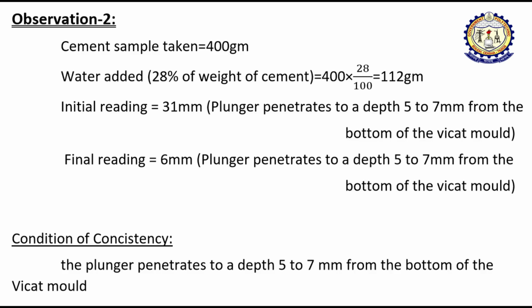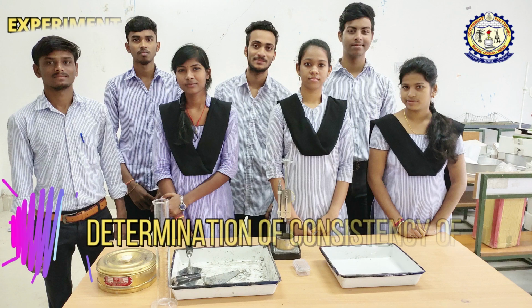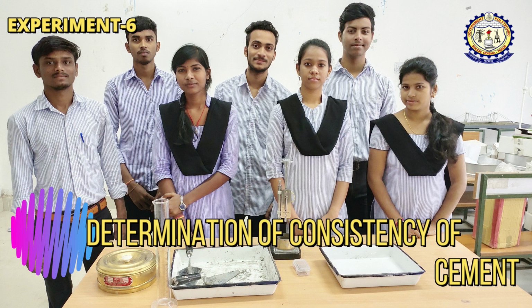In the second observation, we find the final reading is 6 mm, and this value satisfies the consistency condition, so the consistency of our cement is 28%. We can directly say the percentage of water required to achieve normal consistency of cement paste is 28%. After having viewed this video program, you must be able to perform this experiment.